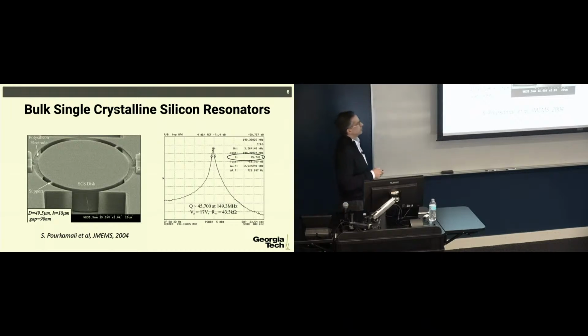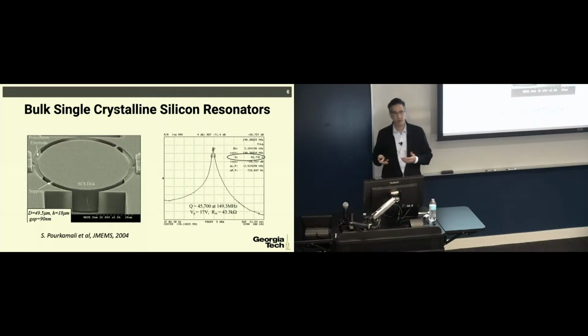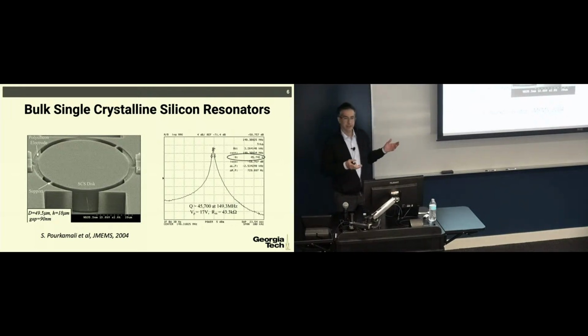So you see that we use that SOI process that we just, recently became available back then at the time. And you see that the thickness is about 18 micron, but the electrodes were made out of polysilicon, filling up these trenches and separated from the body of this disk resonator with a very tiny gap of only 90 nanometer in size. So through the combination of surface and bulk micromachining, we were able to create these structures.